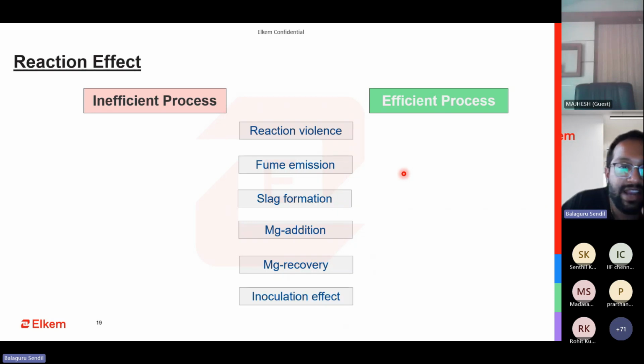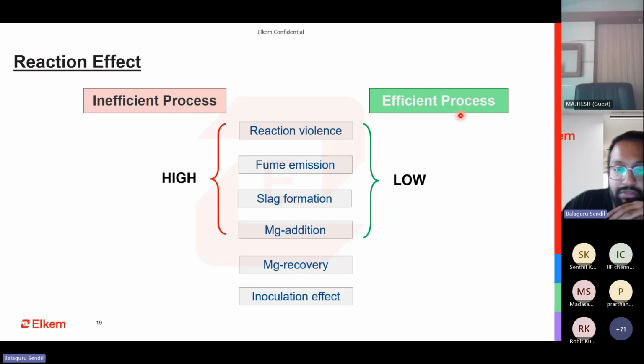I would term this side as an inefficient process and this side as an efficient process. If your reaction violence, fume emission, slag formation, and magnesium addition are all on the higher side, then you have a very ineffective process. If your magnesium reaction is low and fume generation is low, your slag formation will be low too. If, in spite of the reaction violence being calm and the fumes not being extremely high, you are getting a lot of slag, then you need to check the quality of the FSM that you are using, and also the addition percentage and the size. If all these are on the lower side, it is a very efficient process.